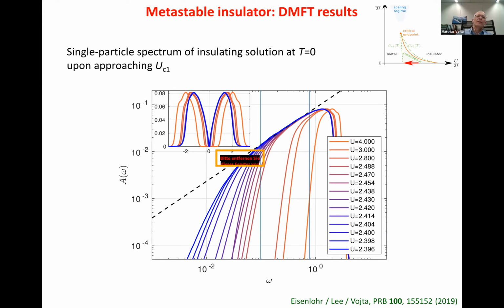Upon lowering U, the curves seem to approach this quantum critical power law, shown here as a dashed line. They don't fully approach it because we are not able to get very close to the end of the coexistence regime due to numerical stability reasons.